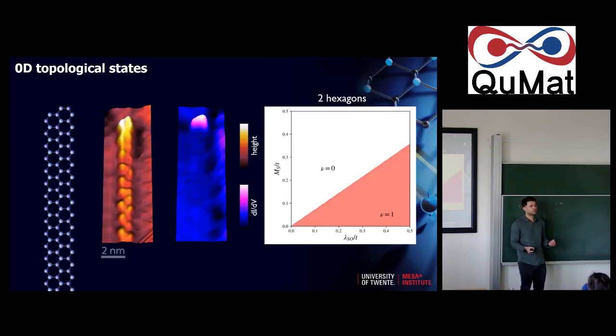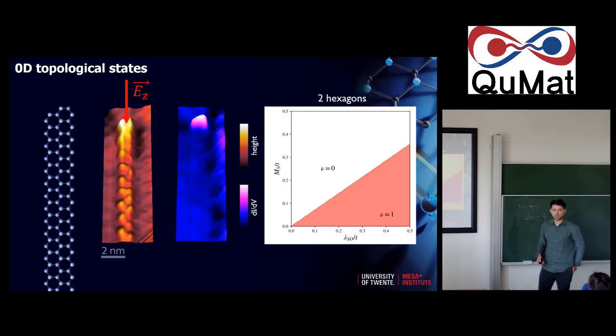Remember that the system is still buckled. So we have this honeycomb lattice that is buckled. Again, here you see your end state. And what comes out very nicely from the theory is that if you find a way to change your staggered mass, the staggered potential due to the buckling, you can go from a topological invariant of 1 to 0 for a given spin-orbit coupling. So you can go from topological to trivial. Again, we can do the electric field trick of the STM tip. As we have our STM tip and we go closer to the surface, we increase the electric field in the system to make it stronger, which translates to a larger staggered mass.